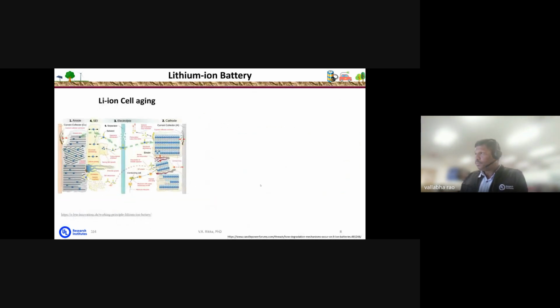If you consider the overall spectrum of the aging mechanisms involved within the lithium-ion cell, there are many. At the SEI layer itself, there is SEI layer breakdown, decomposition, and degradation at different operating conditions. Similarly, there is electrolyte decomposition and gas formation. At the interface of the cathode and electrolyte, there are oxygen evolutions from the cathode surface at different operating conditions, as well as delamination and dissolution of the cathode materials. But whether these mechanisms happen individually at a particular operating test condition, or cumulatively within the cell, it is very interesting and very challenging for developing new test methods for lithium cells in order to improve their safety.